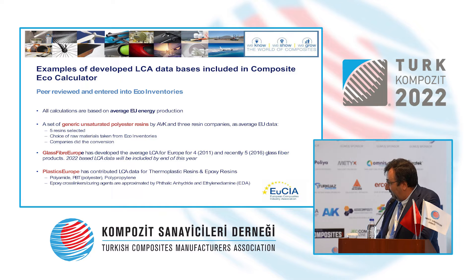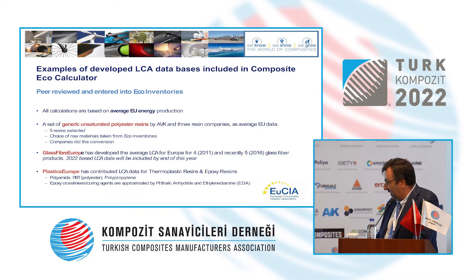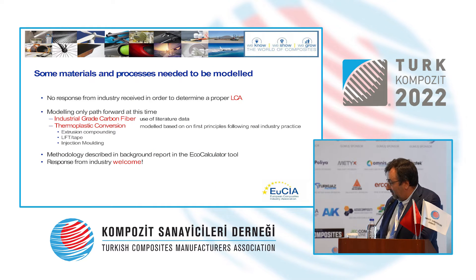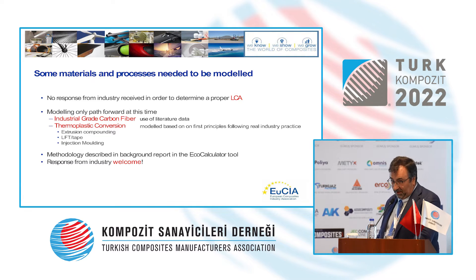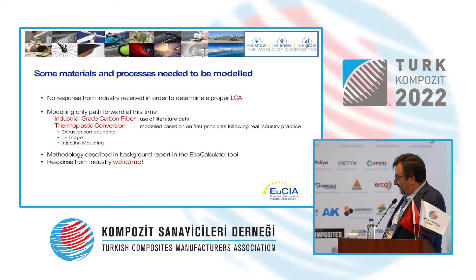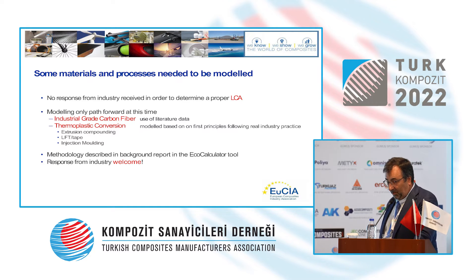LCI data available in the tool includes generic unsaturated polyester resins, glass fibers, and a set of thermoplastic and epoxy resins, covering most resins and fibers in the market. Some processes had to be modeled, including industrial-grade carbon fiber using literature data, and conversion of thermoplastics such as injection molding and extrusion. Contributions from industry are always welcome to expand the range of materials and processes further.